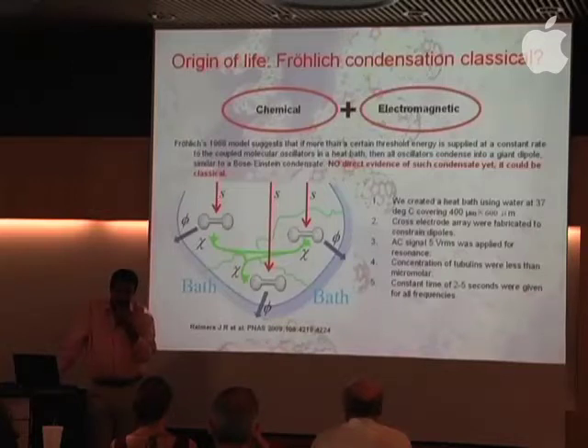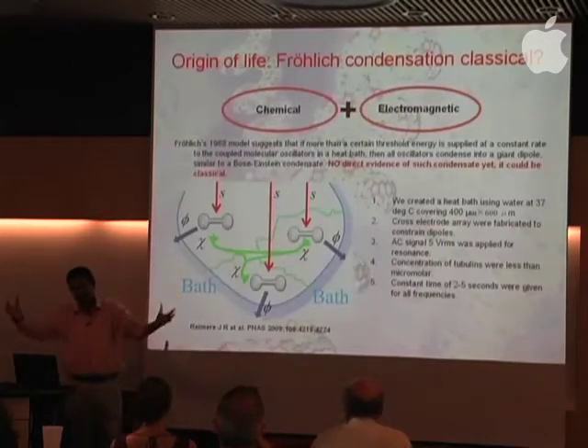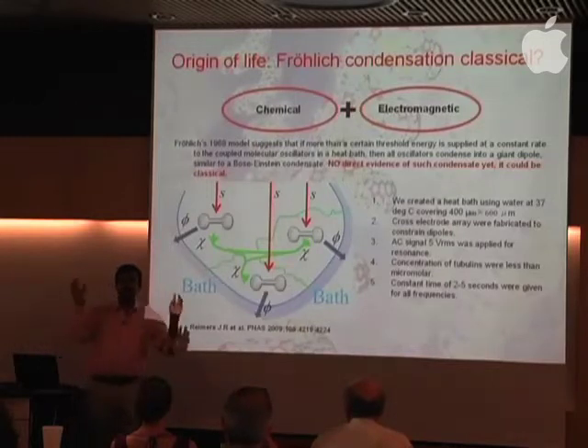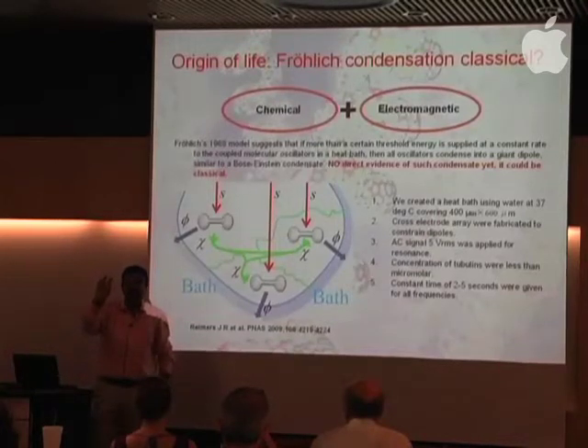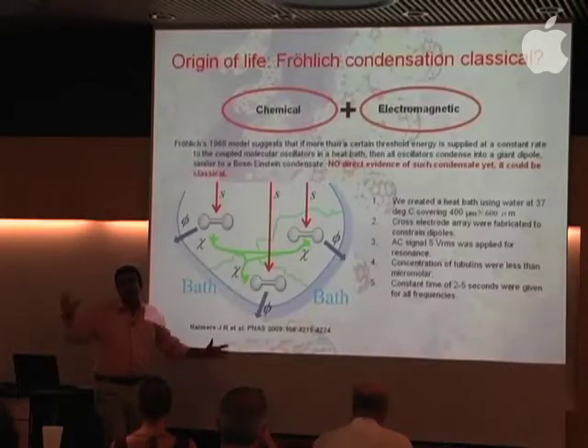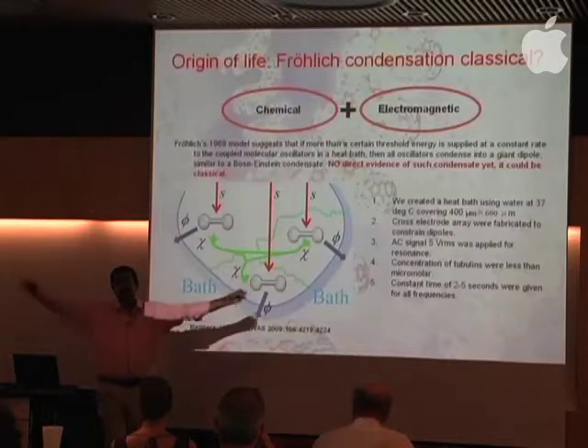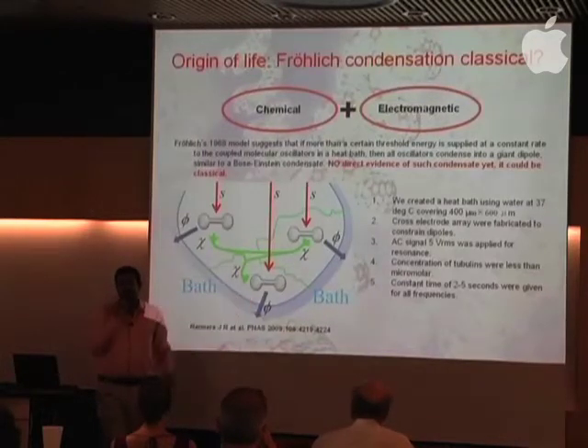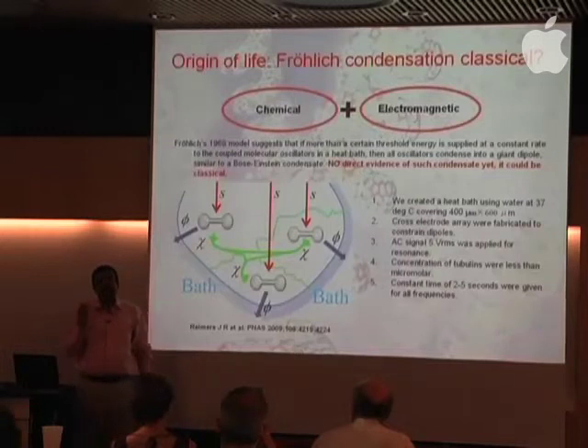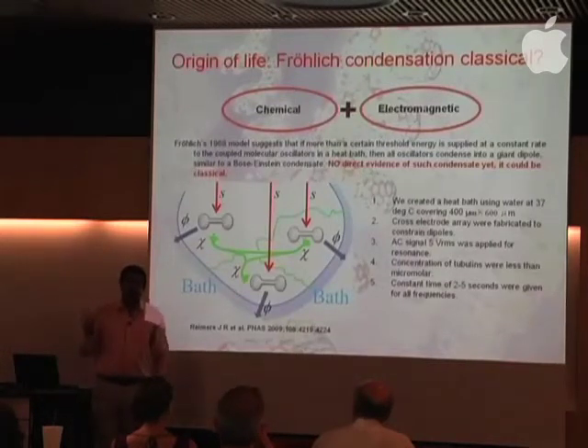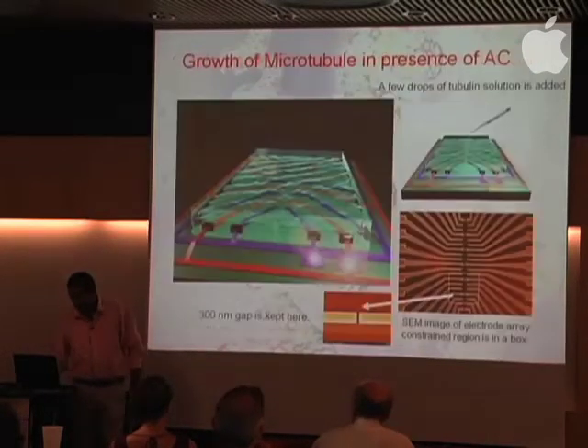And the proposal was something like that. If you have a heat bath or something like this, where heat exchange is not allowed, and you have some dipoles that can oscillate or vibrate, and you have some electric field constraint, if you supply some electromagnetic energy at a particular frequency, a particular energy, you will find that they will all assemble together and form a giant architecture. So this is quite incredible, and this is apparently a fantastic proposal. And if we can do this on a desktop, it is marvelous to see. And we did that actually.